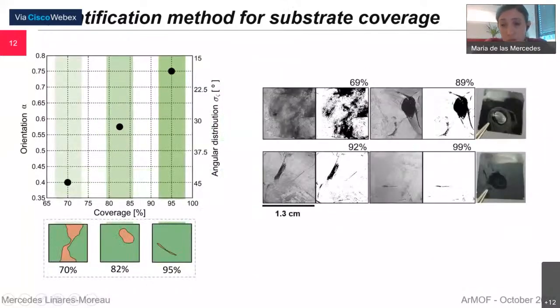And then we also want to evaluate the homogeneity of the film, because due to the deposition method, many times we notice that we have cracks or bubbles or inhomogeneities on the film. So basically, just by evaluating from optical images of the samples, we want to evaluate what percentage of the substrate is coated with a homogeneous layer. This is what we call coverage, and we want to have it as high as possible.